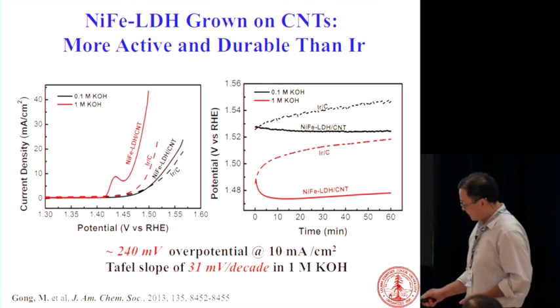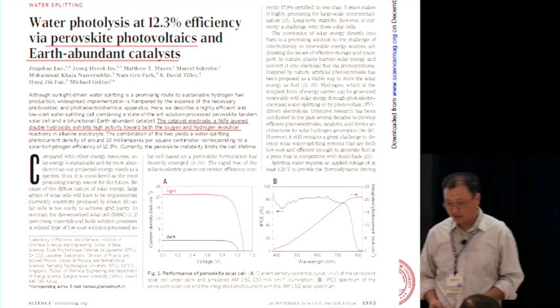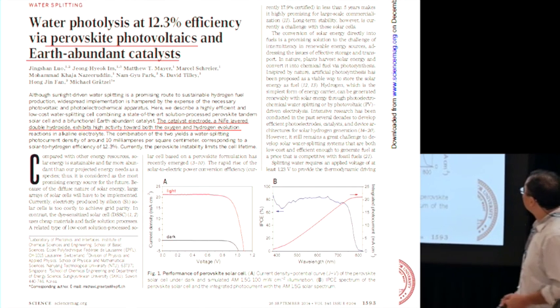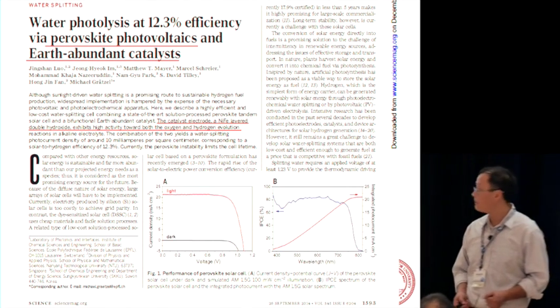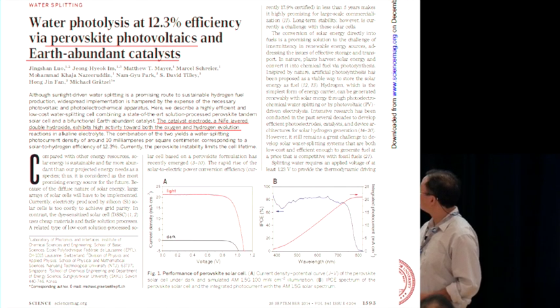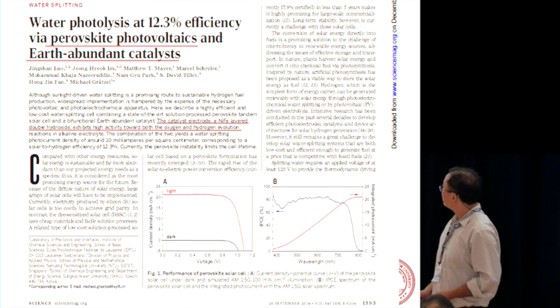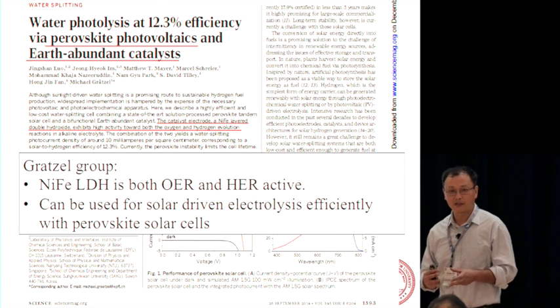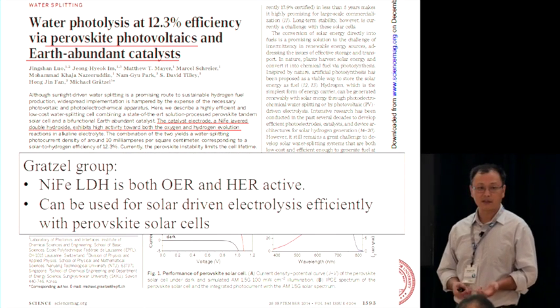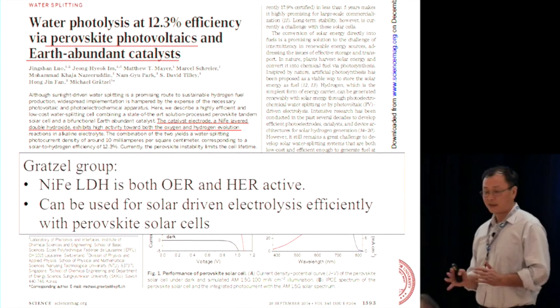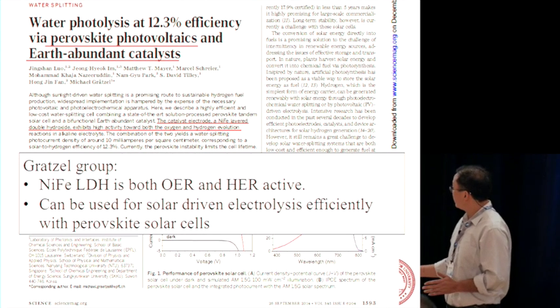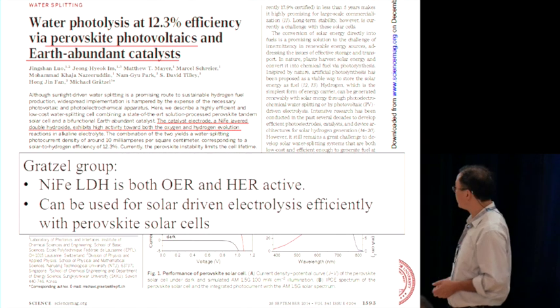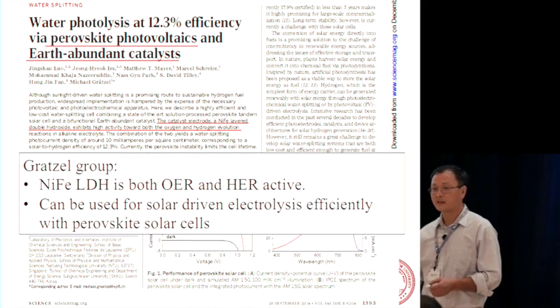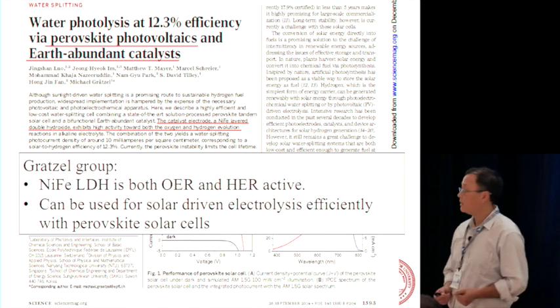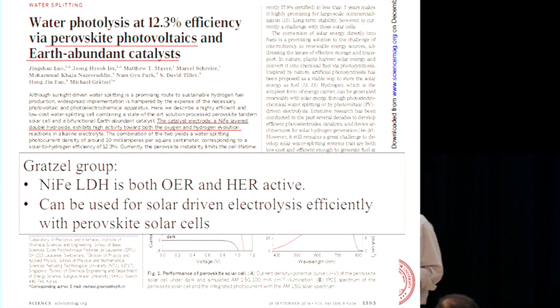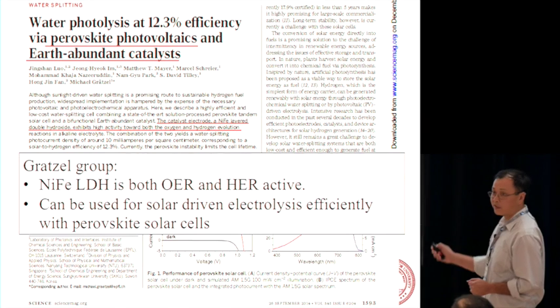So this, after it was published 2 years ago, was very quickly reproduced by many groups in the world, including prominent groups like Michael Gratzel, and they made LDH exactly like ours, and found that this material is good for oxygen evolution, but also it's quite active for hydrogen evolution. So you can actually use it on both sides to get hydrogen and oxygen out. And then also they were clever to put a new solar cell, a perovskite solar cell, to harvest the solar light and drive the hydrogen and oxygen production using the LDH electrodes, okay? Getting a very good efficiency of 12.3%.